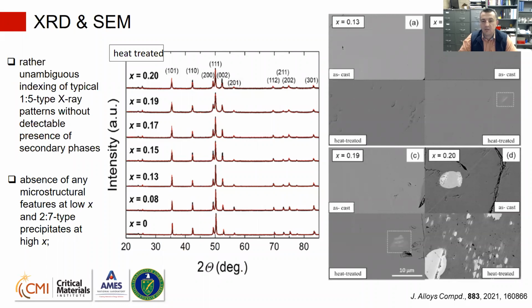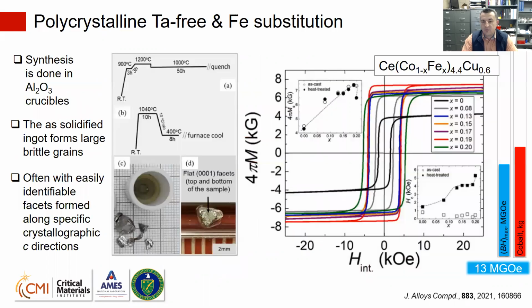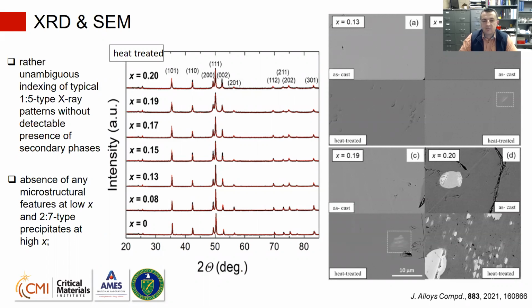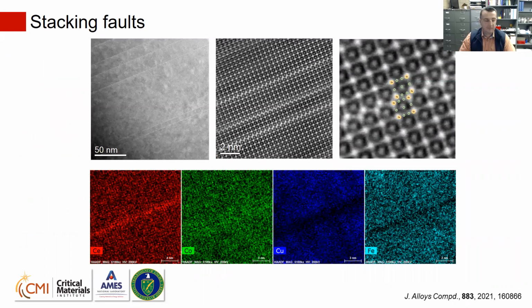When we polished our samples and did the XRD, we wanted to see the microstructure. We wanted to see what is responsible for the exceptional squareness of those hysteresis loops. At low iron contents, we haven't seen anything. At high iron contents, we saw precipitation of a secondary phase, but very disorganized. Usually, if you have a very perfect squareness of your hysteresis loop, the microstructure should be very organized, very nice. So then we decided to look even deeper and found a very interesting phenomenon.